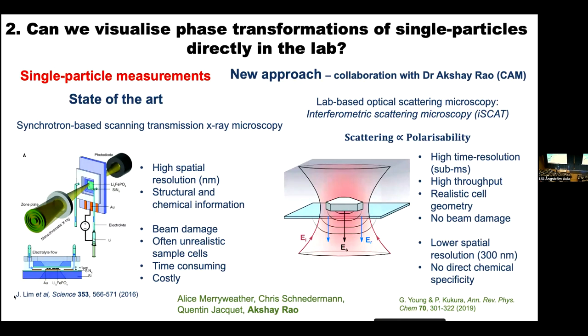And so what Akshay did, and this was coming from the solar PV field, was to try and look at optical methods to look at very fast processes. He was looking at how polarons moved in lead-based perovskites. And so what he did was to borrow from the work of the fluorescent microscopy community, where they come in with a laser, or now even an LED light, you hit a particle, and you get scattering off the particle. And so the scattering is going to be proportional to the polarizability, and you will see a contrast between two different media. The media in this case would be the particle and the electrolyte around it.